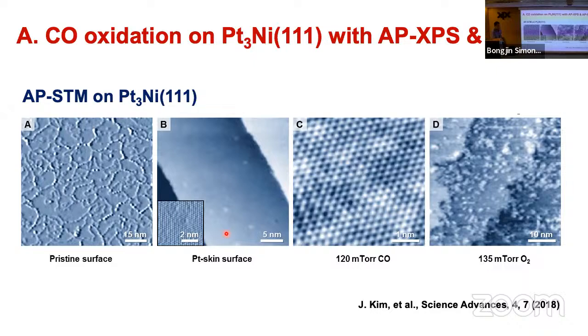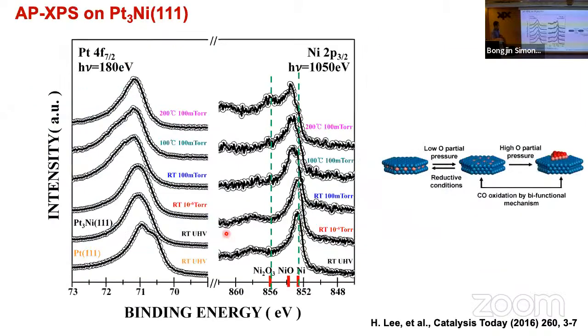You start to see the roughening, and this is actually with the STM, you don't know whether this one is nickel or whether this is platinum. And they saw this one, and then they were questioning it. What are these, these nanoparticles? I mean, these particles that are coming up to the surface. So this was their first measurement with STM, and then we happened to run into each other at the conference, and we discussed, okay, maybe we could do this together.